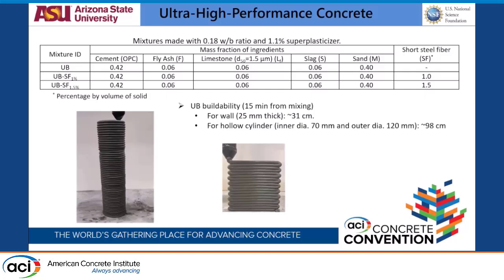For this to be printable: in a cast system, you could put more SP into the mix and make the UHPC flowable and just cast it. But in printing, we need the mix to be flowable enough while you are pumping or extruding it, but stiff the moment it leaves the nozzle. So we tried different superplasticizer percentages without changing anything else. The mix was flowable but buildable at around 1.1% SP content, and we did not change the SP percentage with fiber. With the addition of fiber, the mix gets a little stiffer, but we still had an extrudable mix.